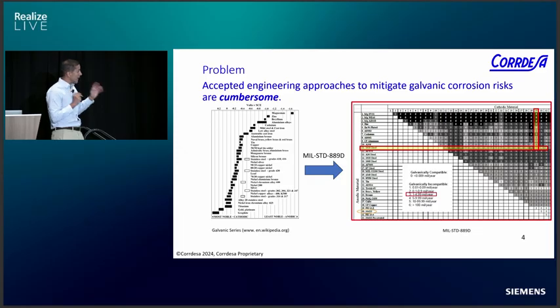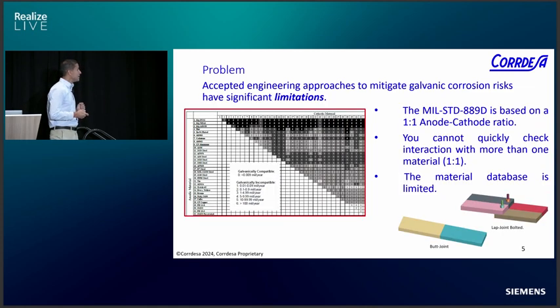This is a method that is now used in the DoD, the Department of Defense, but it has a main limitation. The limitation is that we have to use this with a 1-to-1 anode cathode ratio. Once we change the anode cathode ratio, this doesn't work anymore. We cannot use that anymore. And it's clear that actual systems don't have that 1-to-1 ratio.